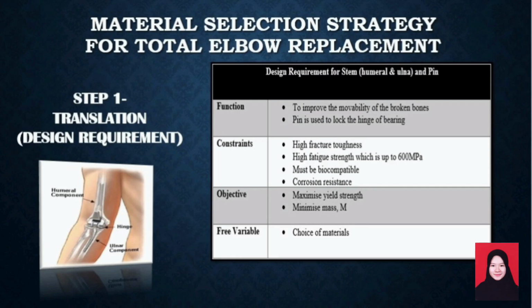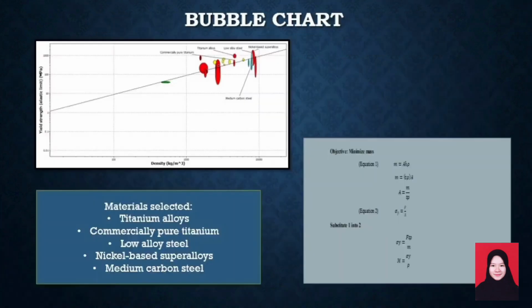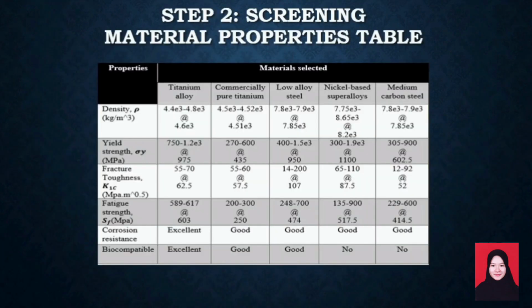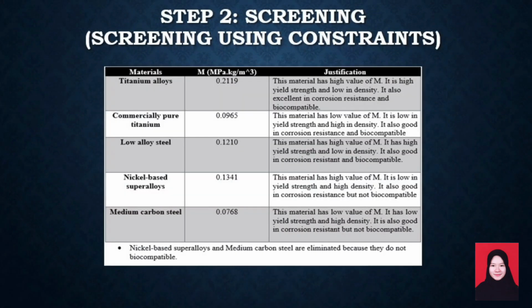Then after determining the design requirement, the materials index is derived as shown in the slide and a bubble chart is created. The materials chosen are titanium alloy, commercially pure titanium, nickel-based superalloy, medium carbon steel and low alloy steel. For the second step, the screening step, the material properties of each possible material are retrieved from CES software. So here are the properties of the 5 chosen materials. Besides, in this screening step, each of us has screened the material using the constraints stated in the design requirement table. From the table, we can conclude that nickel-based superalloy and medium carbon steel are eliminated because they are not biocompatible.